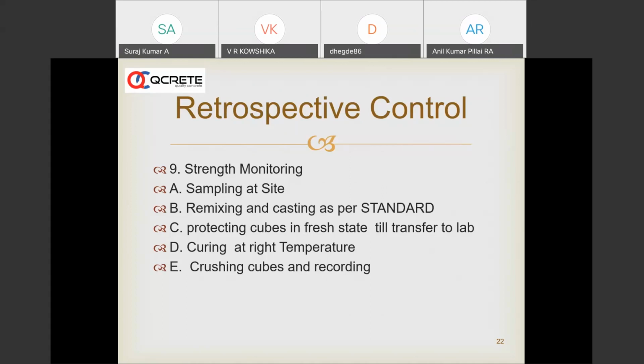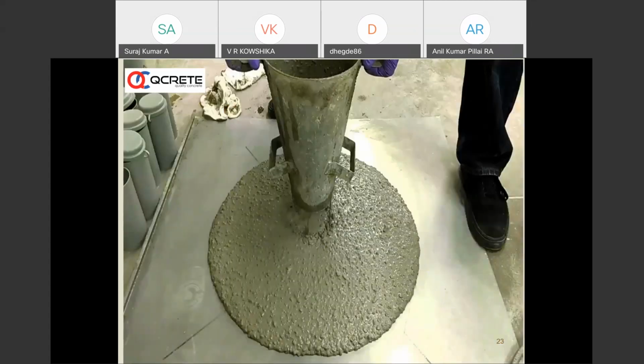These are the set of activities that we do, and you can see some of these things that we do on site. For an SCC concrete, you can see a very cohesive mix, which is exhibited here. No bleeding. So at site, if we are talking about SCC concrete, it has to be bleeding free. It has to be a very cohesive and homogeneous mix.